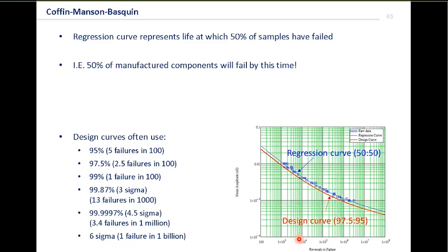Now that sounds like that's a lot of failures. If you're going to be producing 250,000 cars and you're expecting 2.5 failures in every 100, then that's an awful lot of warranty claims, for example. And we dread to think about what would happen in aircraft. The reality is, though, that this is just one statistic in many. So we're applying this statistic to the materials. We've also applied statistical safety factors to our stress analysis, safety factors to our load calculation, and everything else downstream as well. The important thing is to make sure that when all of your statistical reliabilities are combined together, you're achieving that failure rate that you want, maybe a 6 sigma failure rate, 4.5 sigma, for instance. It doesn't mean that every single statistic down that stream has to have that same level. So typically people ask for 97.5 or 95% reliability curves.